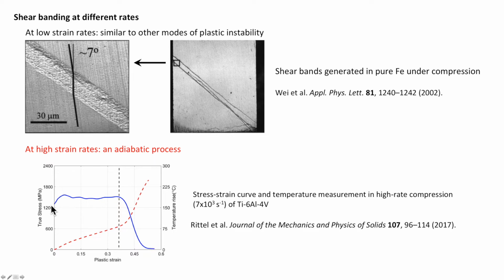The blue curve depicts the stress. The stress level initially remains more or less the same. Then the shear band kicks in and there is a sudden drop of the stress. For the temperature, initially it increases slowly, but when the shear banding kicks in, the temperature rises dramatically. This indicates a strong positive correlation between shear banding and the increase in temperature within the shear band. The rapid increase in temperature has also been considered a major cause of recrystallization within the shear band, which we'll revisit towards the end of this presentation.